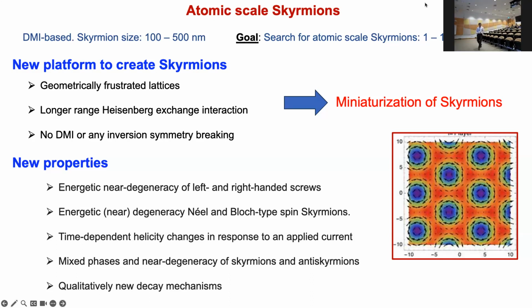So these are centrosymmetric systems with no broken inversion symmetry. Instead, what is prominent here is frustration, both geometric frustration coming from the lattice structure, as well as frustrated interactions coming from longer range interactions. This results in not just the miniaturization of skyrmions, but also imparts a host of new properties.